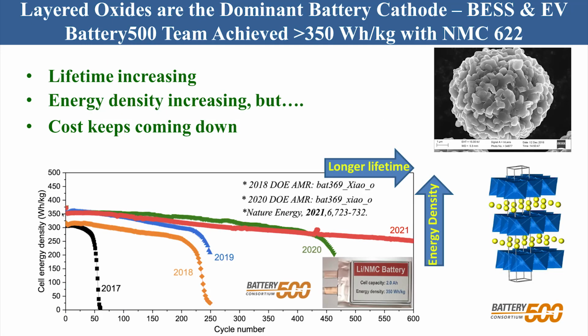And this is the present status of the Battery 500 project. We started out, I think, 6 years ago. We managed, I think, to get about 50 cycles out at 300 watt-hours per kilogram. That's about 50 higher than the commercial cells.